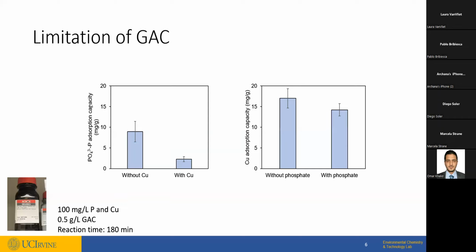Yep, thank you, Ryan Matthew. Ryan Matthew says competition with a second contaminant for active sites. That's a great guess. GAC works via adsorption, so if you have another contaminant, they will both be competing for space. But we thought that even without competition, this performance is poor. Okay, 10 milligram per gram of GAC removal, 15 milligram per gram of GAC removal is poor.